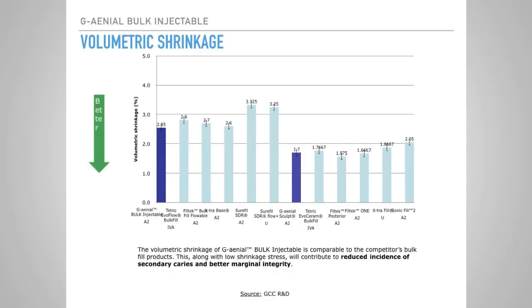So when we're talking about volumetric shrinkage, what we want to see is very little shrinkage, right? We look at all of these materials and compare them, and we see that G-aenial bulk injectable is very, very good when it comes to a flowable material. And we see that the G-aenial Sculpt is even better, but we're concentrating on the volumetric shrinkage of the G-aenial bulk. So it reduces the incidence of secondary caries and gives better marginal integrity because you have this wonderful low shrink material.